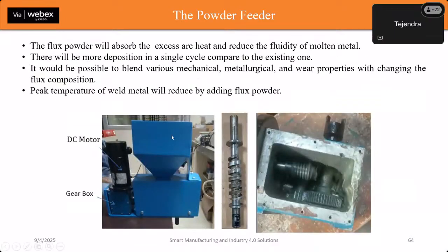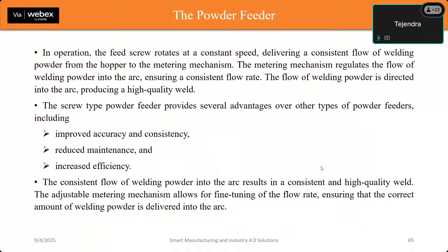This was the exterior portion of the powder feeder. This was the screw that we used to feed the powder from the hopper to the nozzle, and this was the gear train that is used to move the screw. So basically, in the operation of the powder feeder, the feed screw rotates at a constant speed, delivering a consistent flow of the welding powder from the hopper to the metering mechanism. The screw type powder feeder provides several advantages that we have already discussed, and it provides a consistent flow.